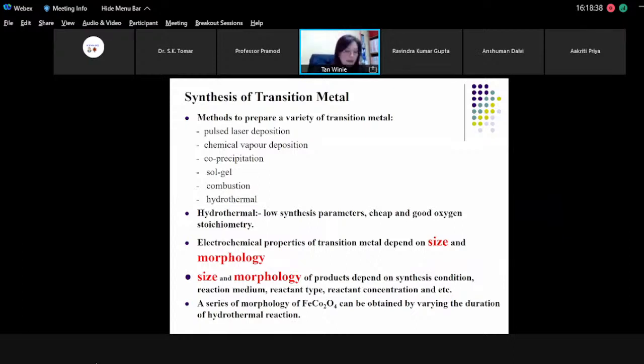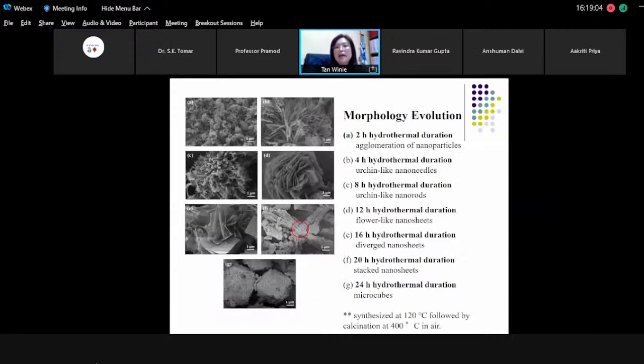In this hydrothermal process, the size and morphology can be influenced by the synthesis conditions, such as the type and concentration of reactant, reaction medium, and so on. So here I would like to share with you how we vary the duration of the hydrothermal reaction, and then we can get a series of morphologies of the iron cobaltite. So this is the morphology evolution of the iron cobaltite by varying the hydrothermal duration.